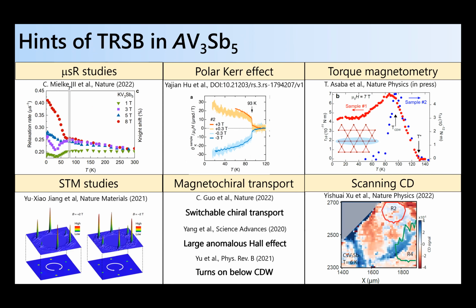Just to clarify, Kerr effect will not see antiferromagnetism, that's correct? It can see Q equals 0 antiferromagnetism in certain cases. Basically, if you have a multi-site unit cell with two magnetic sites and the magnetic order doesn't enlarge the unit cell, you can see that in some cases. Altermagnets are an example. Is it known that we can see altermagnetism with the Kerr effect? Is there any measurement? Yes, from a while ago, they weren't called altermagnets, but there are classes of antiferromagnets where Kerr effect is known to occur. Peter Armitage told me a bunch of them recently, and I can't remember them now, but I'll try to remember.